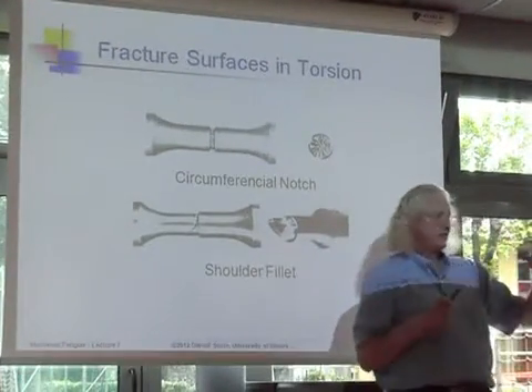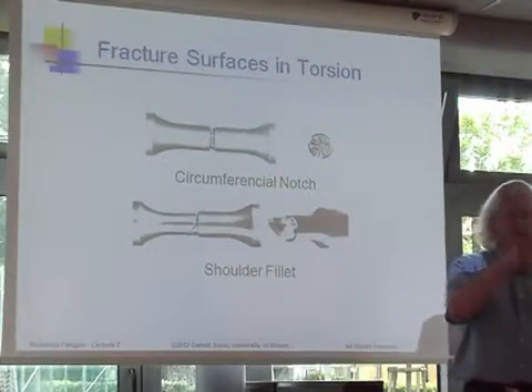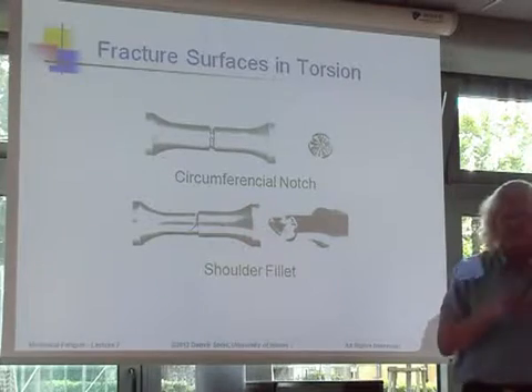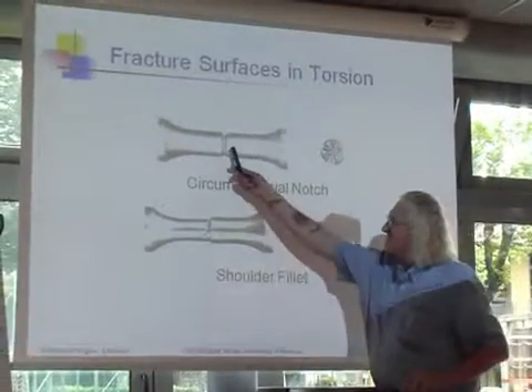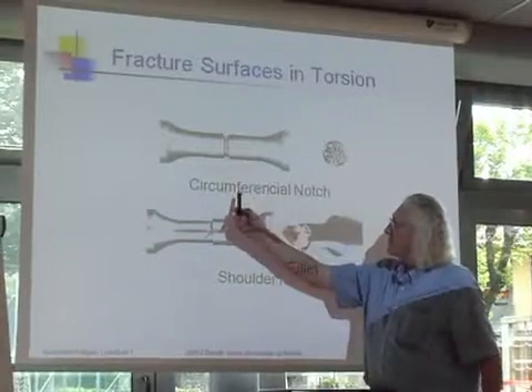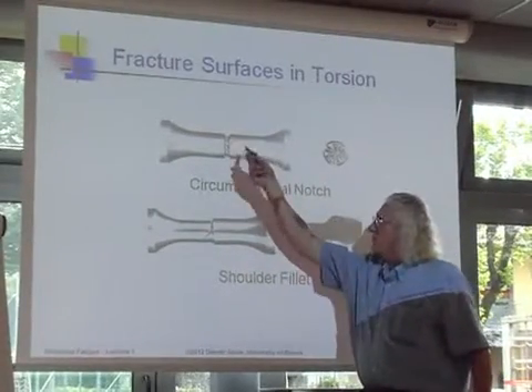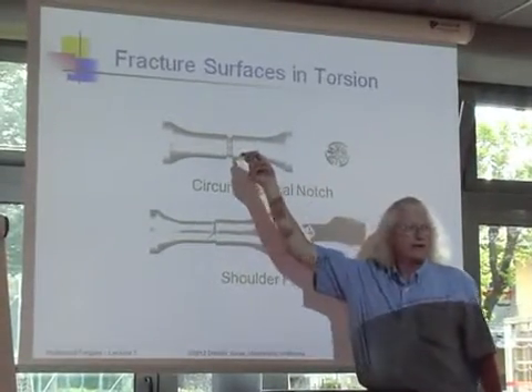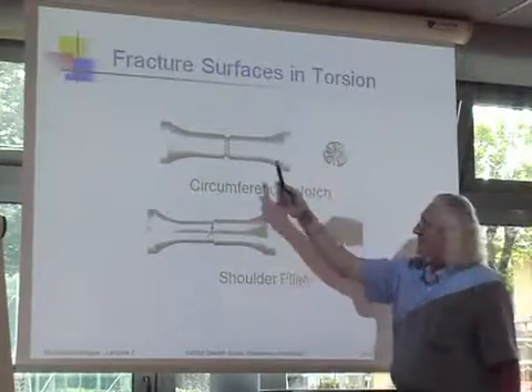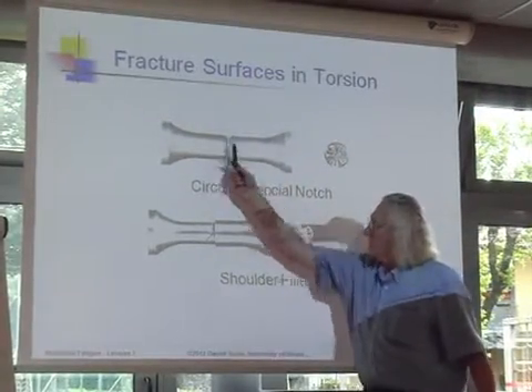That doesn't happen in tension. That's why torsion is the dominant failure mode everybody is really concerned about, because if I had these same geometries in either tension or bending, all the crack growth would be through the thickness trying to break it. You wouldn't have these scenarios where the cracks try to grow out of this and grow along here.